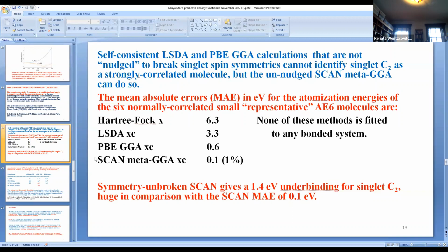The strong correlation is significant, but it's still comparable to the error that those functionals make. For instance, the mean absolute error in electron volts for the atomization energies of normally correlated small representative molecules - this is the so-called atomization energy 6 set.